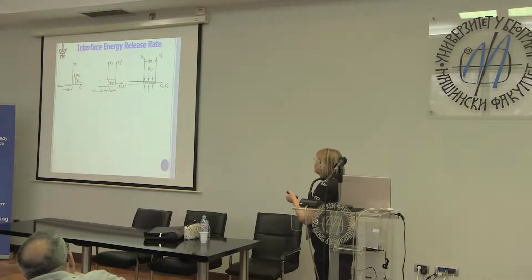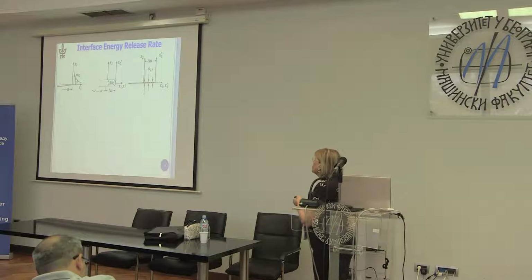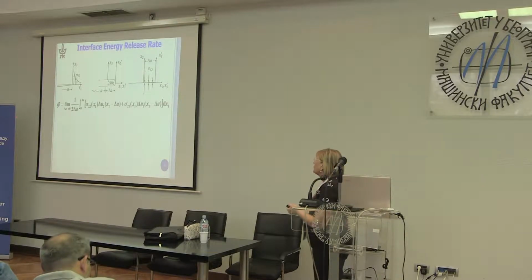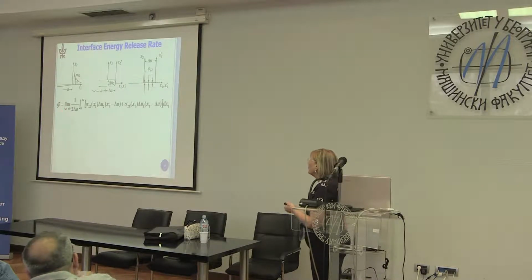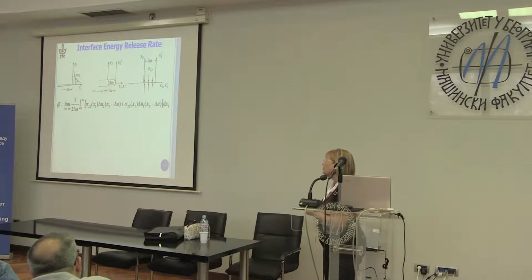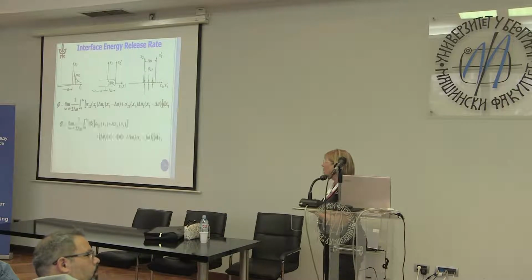So let's go back. So the crack has a delta A, and we're going to close this crack, and we want to calculate the work done in closing the crack. Only this part; but we need to leave it open over here. This part is open, this part is closed. Okay, so let's look at the mathematics of it. So the energy release rate is the work done in closing the crack. So for work, I have 1/2, and so I have sigma 2,2 going through delta U2. This is the mode 1 energy release rate, and this is the sliding, the mode 2 energy release rate. It's for this virtual crack extension delta A, and we take delta A going to 0 and we get the energy release rate. So we have the energy release rate for both opening and sliding crack faces.